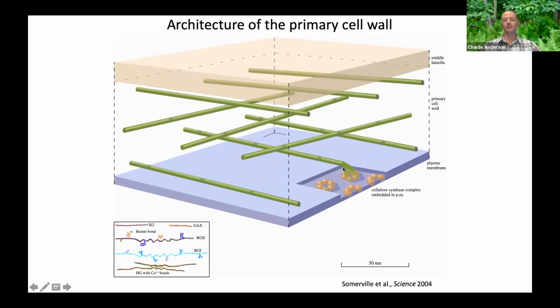And these cellulose microfibrils are long and linear. They're actually more curved than is shown in this diagram. They tend to weave throughout the layers of the cell wall. But they are fairly straight, and they're long and skinny. They have a very narrow width. They're usually about 3 nanometers in diameter, but they can be several microns in length. And they form this really important scaffolding that helps hold the cell wall together and give strength to the cell wall, but still allow for enough flexibility for growth.